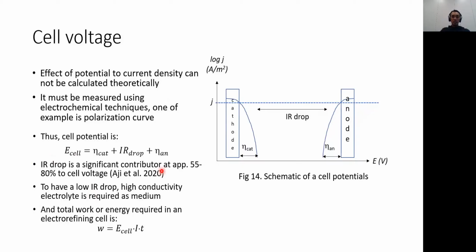From what I read in publications and what I measured in the lab, IR drop is actually quite significant, because cathode and anode are very conductive, especially if we talk about silver. Silver is the most conductive material that exists, even better than copper or gold, losing only to graphene, if I'm not mistaken. So IR drop is very significant. It can be 55 to 80% of the total cell voltage. So basically, industry can pay 80% of their energy for something that is not in the process itself. It's just the cost of the medium.